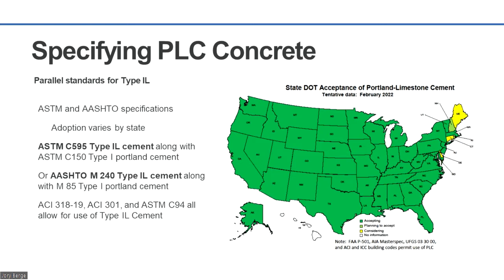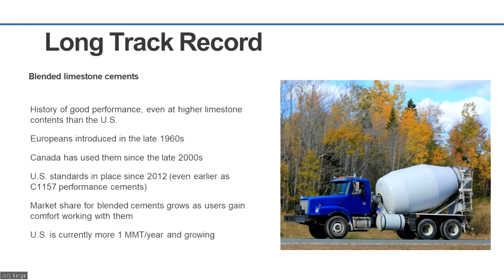And that's just due to the processing of it after the clinker is made. They're typically ground slightly finer, so that gives us some early strength generation. And it also may or may not speed up your set time. So the things that you're thinking in your head for performance are actually the opposite of what typically happens out there in practice. And if you do need to fine tune your mixtures, it might just take a slightly different water demand, a slightly different admixture dosage, but it's not night and day from ordinary Portland cement mixtures.